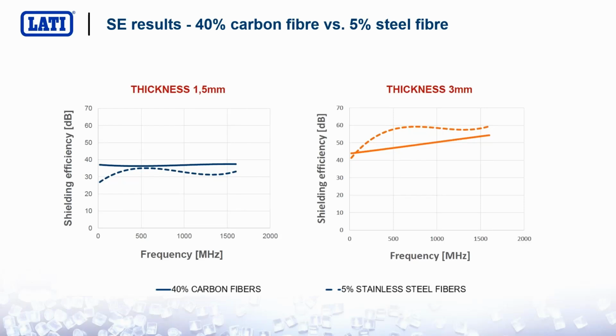As you can see, this is also a comparison of carbon fiber with steel fibers. 40% carbon and 5% steel perform more or less the same from a shielding efficiency point of view. Now let's jump into the next experiment. What happens if we mix steel fibers with carbon fibers? So we make a compound which is actually featuring steel fibers and carbon fibers at the same time.